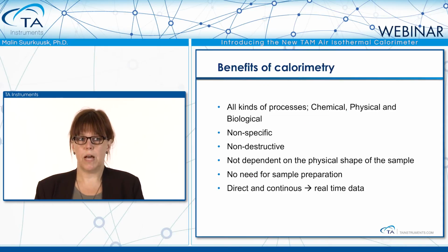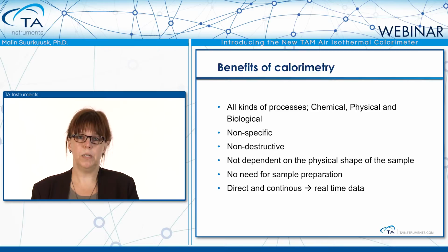So the benefits of calorimetry is that we can measure all kinds of processes: chemical, physical, biological. It's a non-specific technique, meaning that we are measuring everything that goes on in the sample, so you do not have to specify the response you're expecting and what you're going to analyze afterwards. If there is something going on, you will measure that in the heat flow calorimeter. It's non-destructive, so if you see there is something going on, we have not changed the sample in any other way, and you can take it out of the calorimeter and do further analysis afterwards.